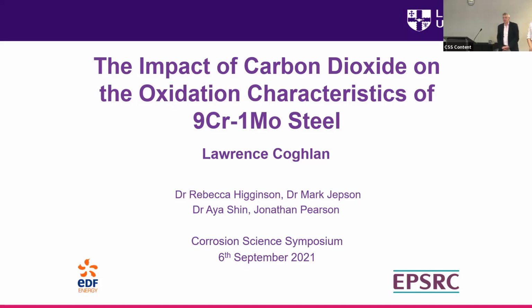Hi, Lawrence. Thanks for the presentation. Quick one. Have you looked at the thermodynamic stability and oxidation of the carbides, in the sense that the carbides are expected perhaps to decompose and release the carbon and the chromium, when the chromium is subsequently oxidized? Only with what I've seen. I haven't really looked into it specifically, but I think you do see evidence in some of the breakaway samples of how, with the carbides, once they've been oxidized within the oxide, you can clearly see where they were before, but I haven't looked into it specifically.